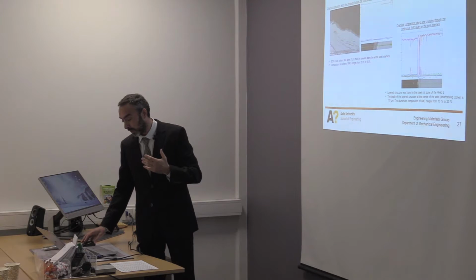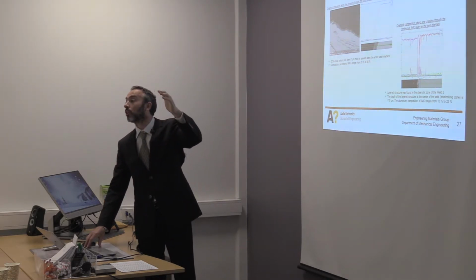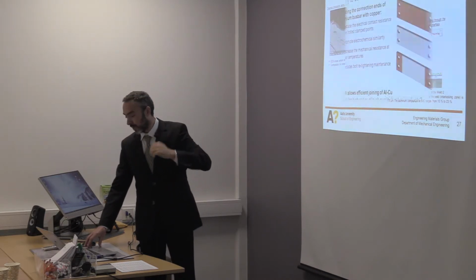Very important always is the control of the intermetallic compounds between these dissimilar materials, and we reached very low levels of aluminum in these intermetallic compounds, which is the best condition, and also a layered structure that performs very well. So overcoming the problems of high temperature processing of the materials, where these intermetallic compounds compromise the joint.